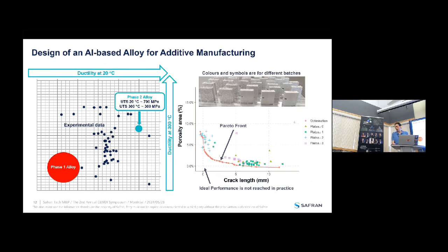Onto the aluminum-based alloy design and process optimization. We're in the context of finding what we call high temperature aluminum alloys. So we're not talking about 500 degrees Celsius, we're talking about 150, 200, 250 degrees Celsius applications. The context is also additive manufacturing, and you can see the kind of technological specimen that could be built. You can see there's a notch that creates a stress concentration. The idea is to provoke cracking and to judge the processability of the alloy using additive manufacturing as a function of the crack length. But you don't build actual parts with notches like this.